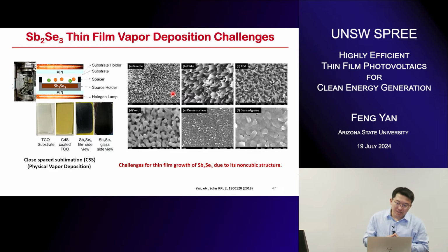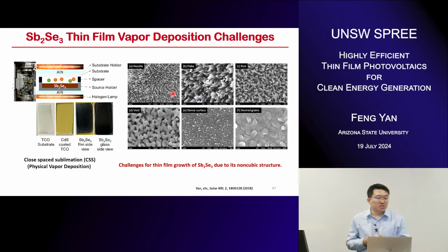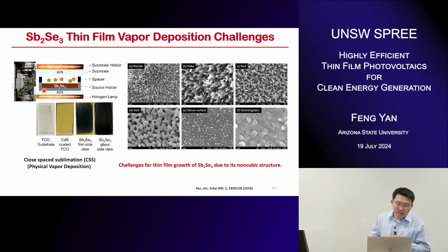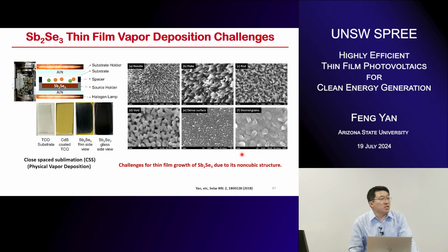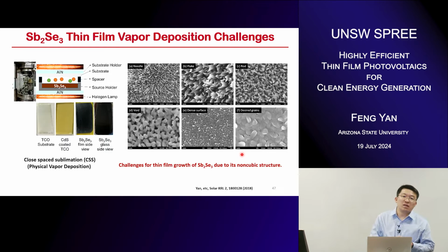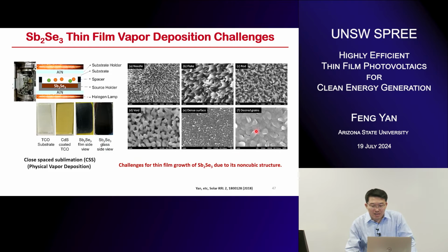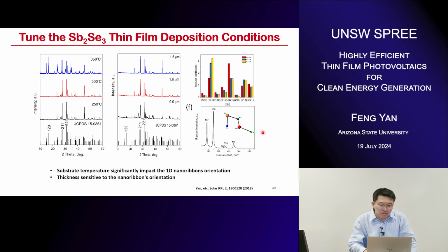You can see that. But after you tune the growth conditions, here is a very simple closed space sublimation. You can put the powder inside and vaporize the film easily. And after tuning the growth conditions, pressure, temperature, or even substrate temperature, whatever, we can finally get the desired film. Then you can see that the efficiency significantly relies on the film's crystal orientation and crystallinity. The critical growth conditions are the substrate temperature or the source temperature, and also the film thickness.